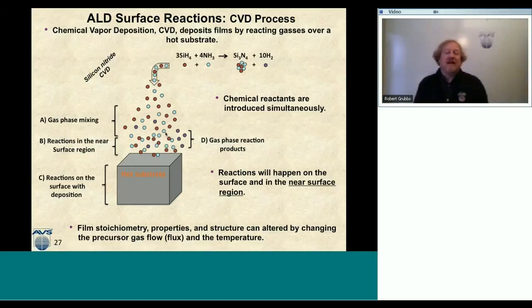But CVD has this unique feature where you get surface reactions in the near surface region. And I'm pointing that out because ALD does not have these reactions in the near surface region. So that's one of the two primary differences in CVD, is that you get this near surface reaction taking place right above it. Now, the fourth step would be that there are gas phase reaction products that either leave the surface or can actually get incorporated into the film.